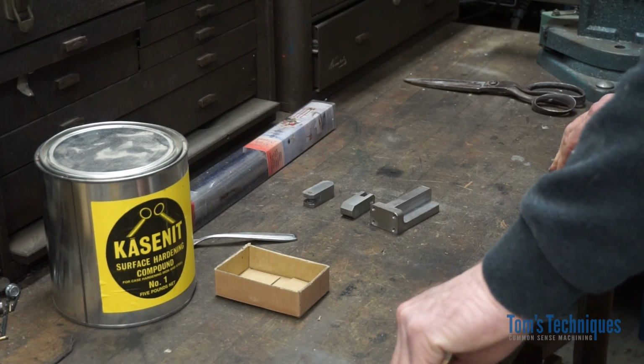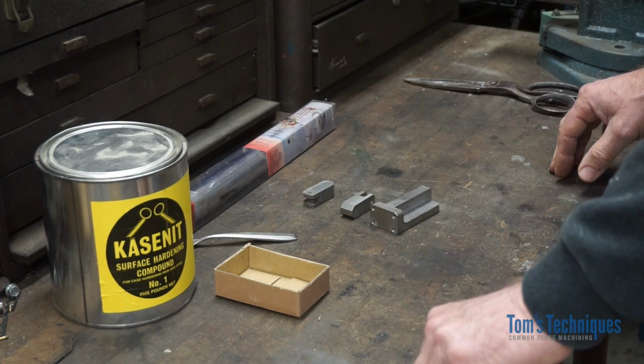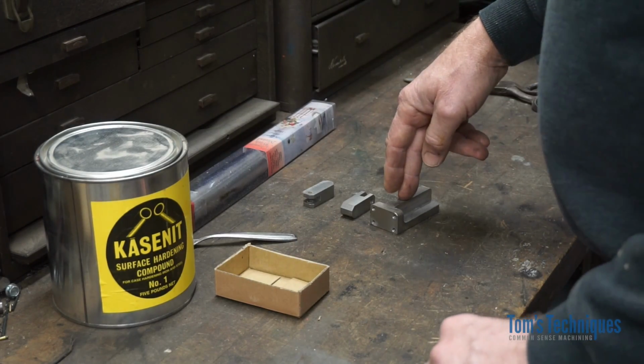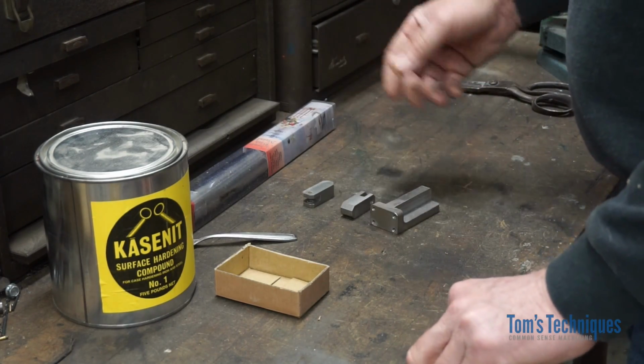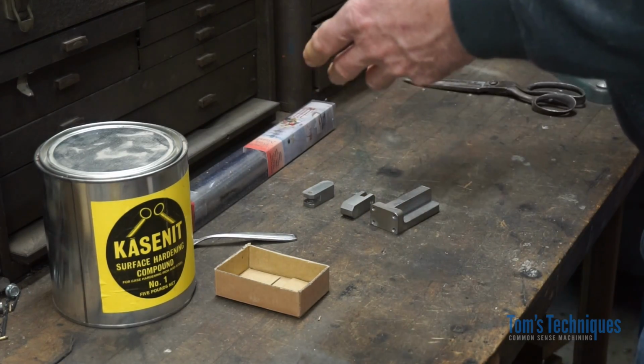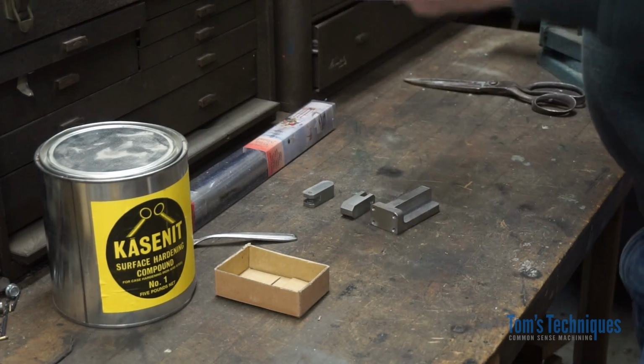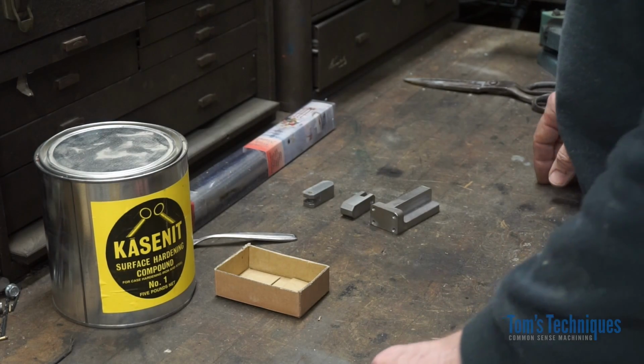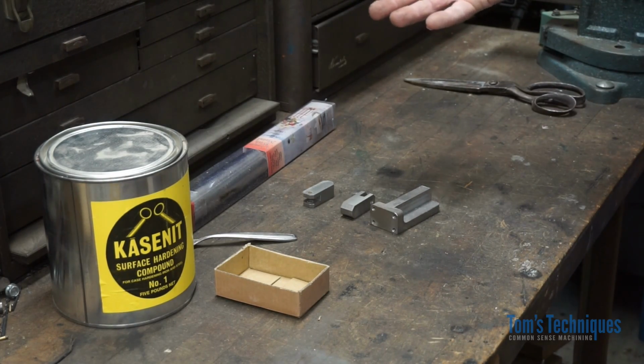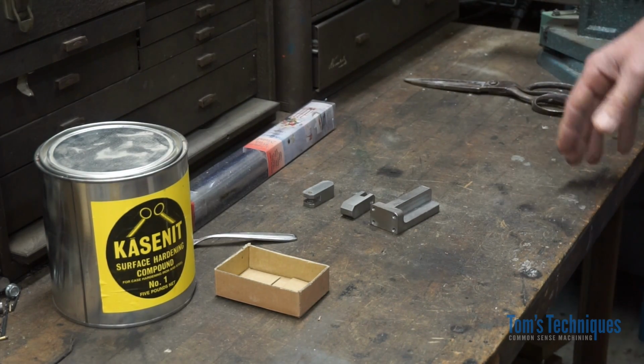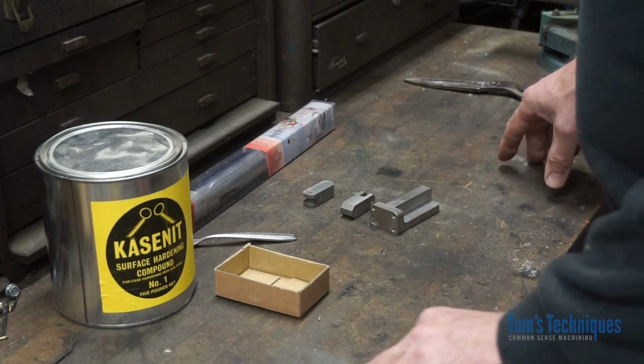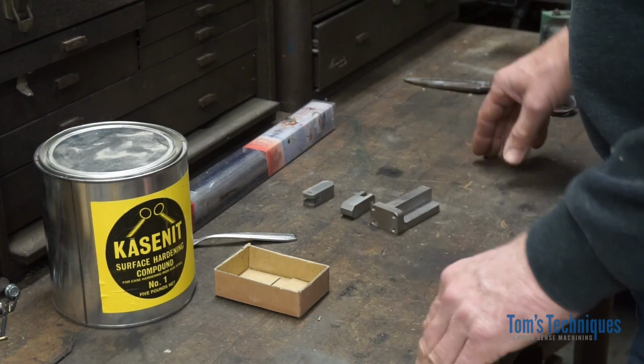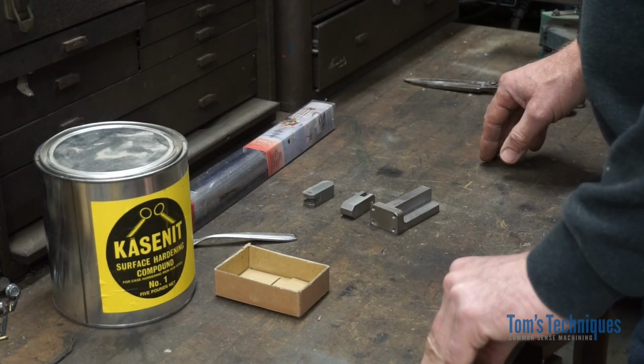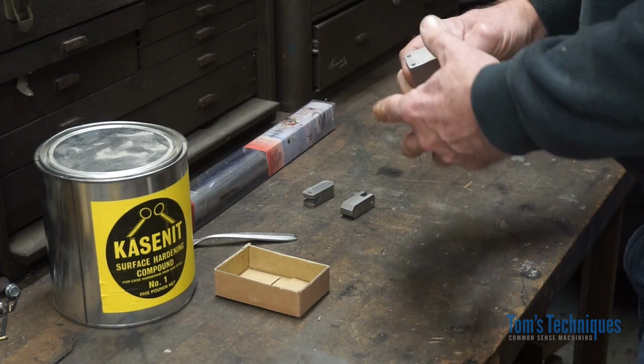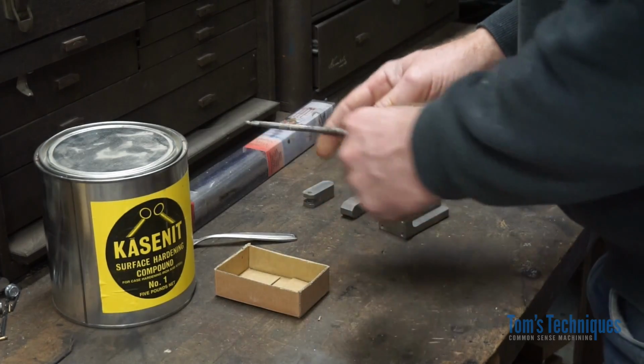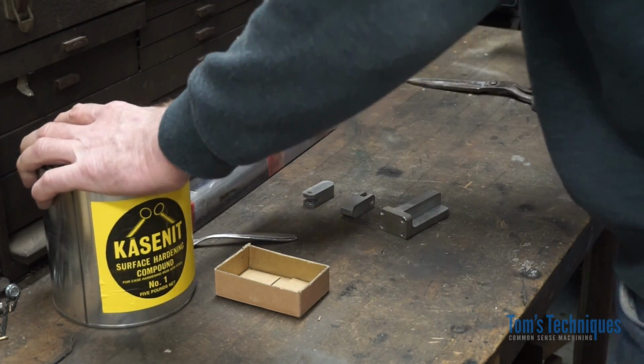Case hardening is the process of introducing carbon into the surface of the part at high temperature until the surface of the part has enough carbon in it that it can be hardened. And once that point is reached, the part is quenched in cold water to harden it. So first thing we need to do is add carbon to the surface of these parts, and we do that by a process called packed carburizing.